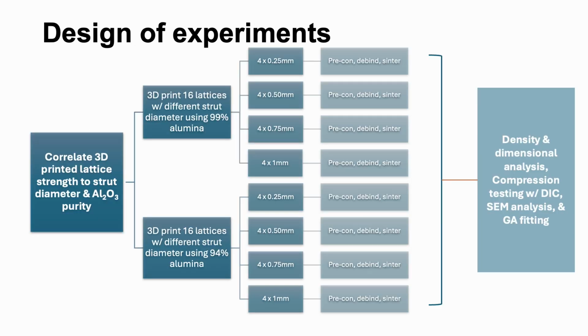So the goal of this work was to correlate the mechanical strength of the lattices based on its strut diameter and alumina purity. So what we did is we 3D printed lattices using 2 different alumina purities, a 99% alumina and a 94% alumina. We also made 4 of each lattice type and varied the strut thickness. So there were a total of 16 lattice structures printed for each alumina and 32 lattices total overall.